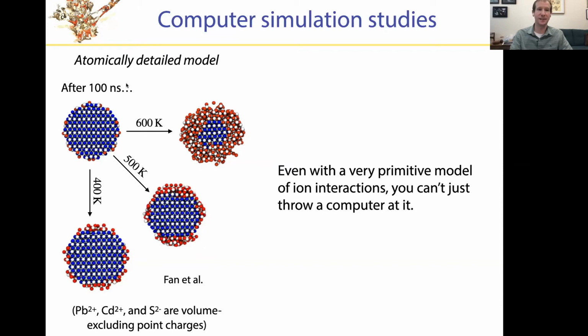When we advance atomistically detailed descriptions of matter, we can do so typically at most for a microsecond. So in this case, they managed to run for 100 nanoseconds or so. And at the kinds of temperatures where cation exchange actually proceeds, you see that very, very little happens. You see some exchange at the boundary here, but no significant progress of that reaction to the interior.